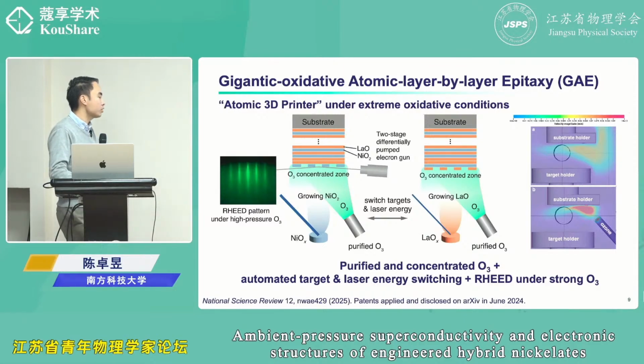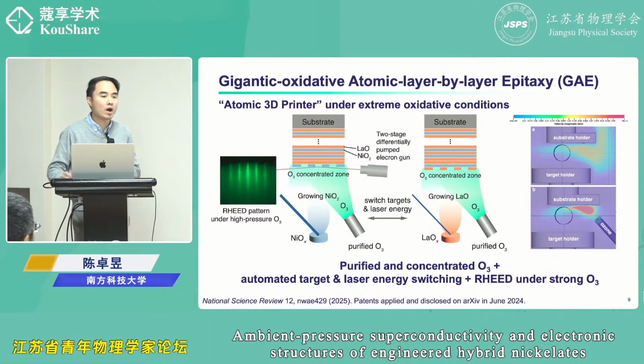First is to use a highly purified ozone. We have put in a lot of effort to make the ozone really pure, and even within the chamber, it can generate a concentrated ozone and also very strong oxidation. Ozone is known to be very easily decomposed to oxygen, so in the transport of ozone, we first purify it using this liquefaction way, and then the ozone is evaporated and transferred to the chamber, and all along this way it is decomposing. So we put in some effort to make sure that even inside the chamber, it still has quite a high ratio.